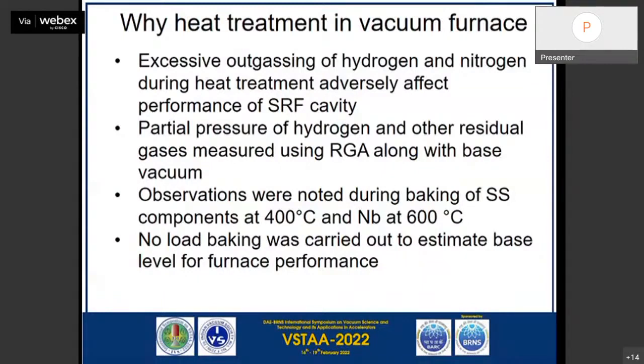As we all know, the hydrogen gas dissolved in the stainless steel during the production of furnace and vacuum components is the largest contributor to the outgassing rate of stainless steel. Excessive outgassing of hydrogen and nitrogen can adversely affect the performance of SRF cavities. Hence, hydrogen outgassing is a critical parameter. Therefore, trials have been carried out at no load condition, with SS components and niobium sheet, to specifically understand the hydrogen outgassing load. The partial pressure of hydrogen and the other residual gases is measured with the help of RGA. So, next slide.